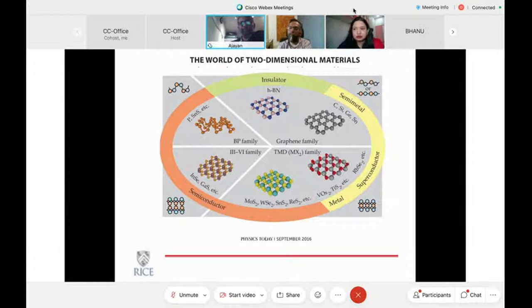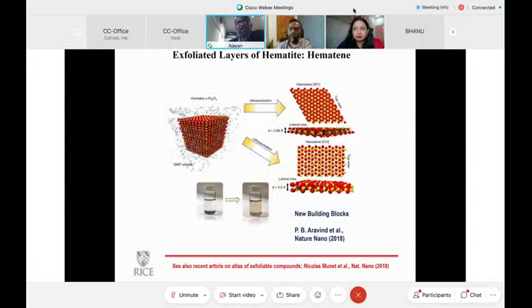So these are available. Now, in terms of creating these super thin layers or 2D materials, there are multiple approaches people have taken. The simplest one, of course, is physical exfoliation, which is essentially a scotch tape peeling method, right? That's where the graphene work started. Of course, that has limitations because scalability issues are there. The related technique that people have used quite a lot, and this allows you to produce layers in bulk quantities, is chemical exfoliation. You can take a material and put it in a solvent with the right kind of surface tension, and you can apply some kind of force using ultrasound or microwave. These exfoliate pretty nicely along the weak interlayer forces.